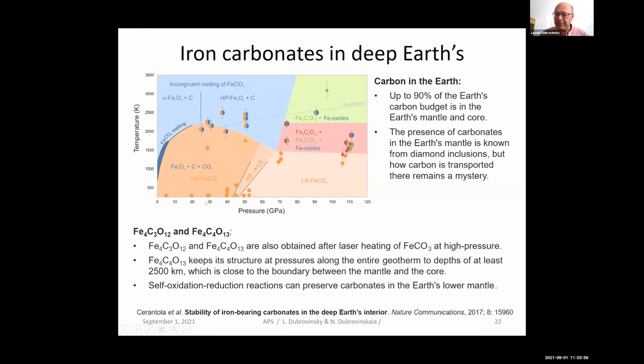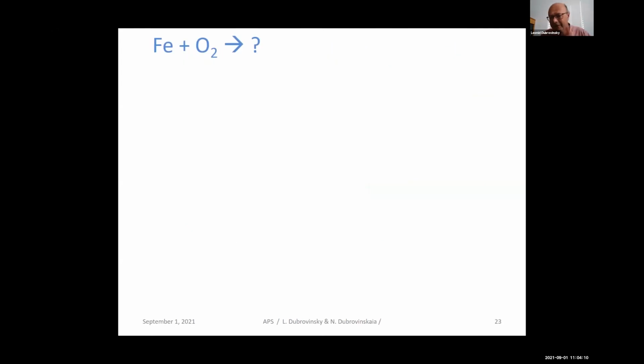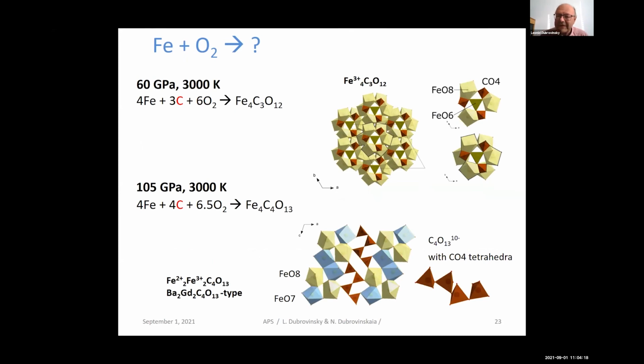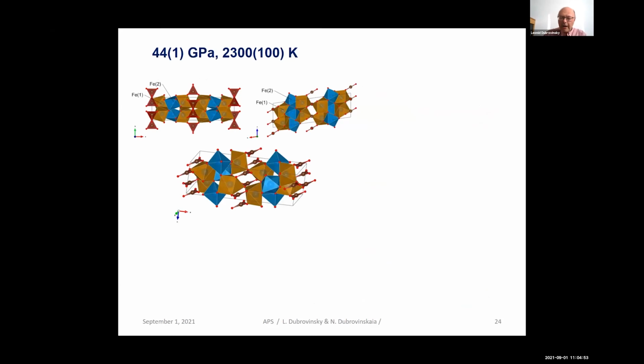It's always a question whether this can be produced only starting from already oxidized carbon, or whether it may be produced from diamond. Well, in one of our series of experiments, we loaded iron and oxygen, and what we saw as a product of the reaction were the same orthocarbonates which we originally observed only as a product of decomposition of FeCO3. It means that if the oxygen fugacity is significantly high at high pressure, we can easily oxidize carbon, or we can have oxidized carbon. I do not know if it's oxidized by oxygen or whether it involves changes in the oxidation state or activity of iron.